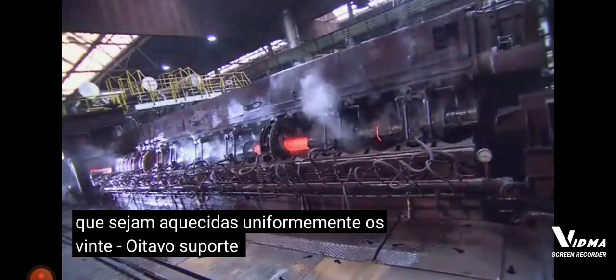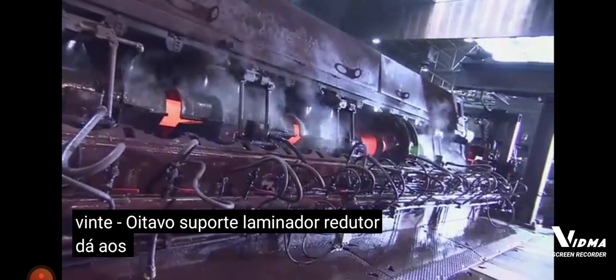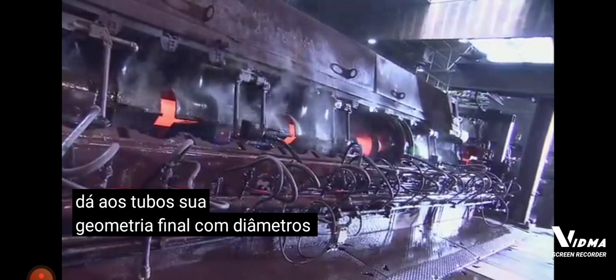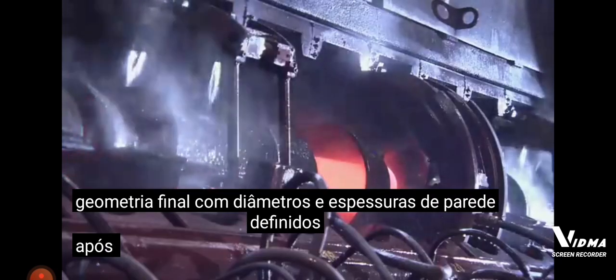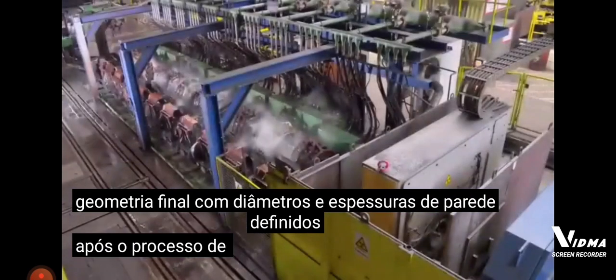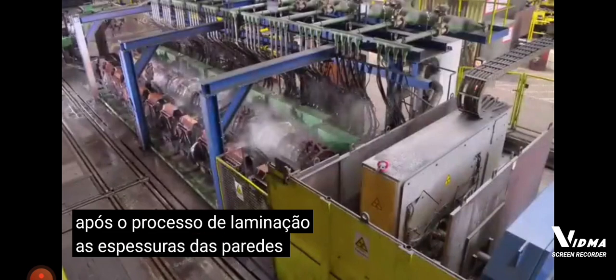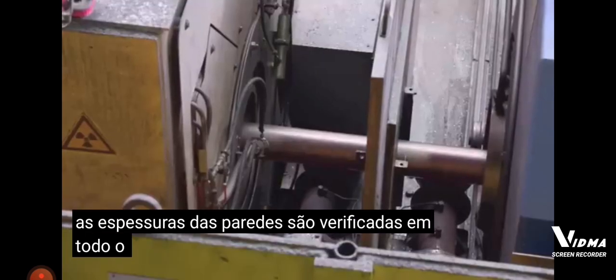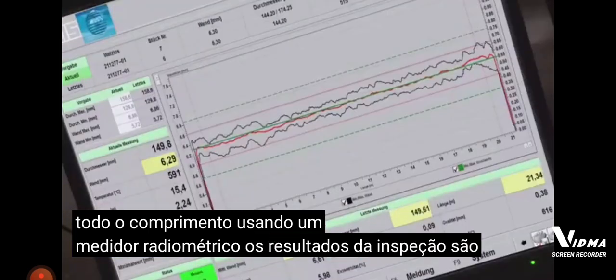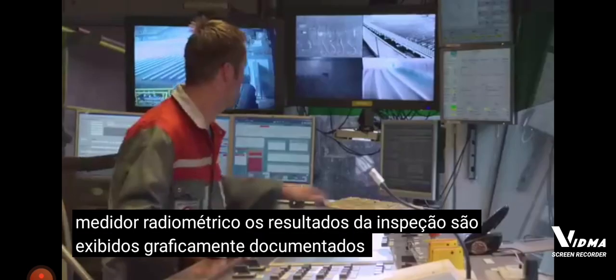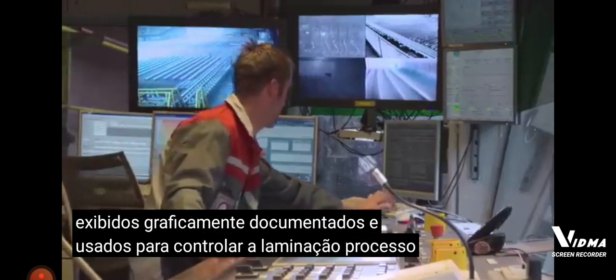The 28-stand stretch reducing mill gives the tubes their final geometry with defined diameters and wall thicknesses. After the rolling process, the wall thicknesses are verified over the entire length using a radiometric gauge. The results of the inspection are graphically displayed, documented, and used to control the rolling process.